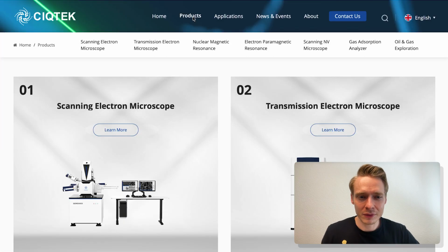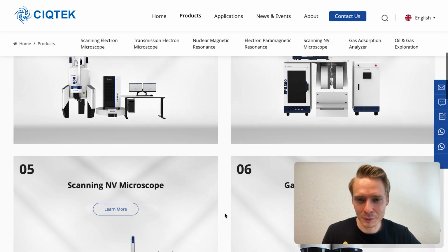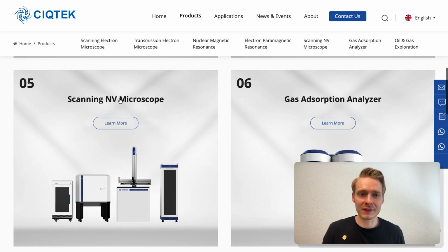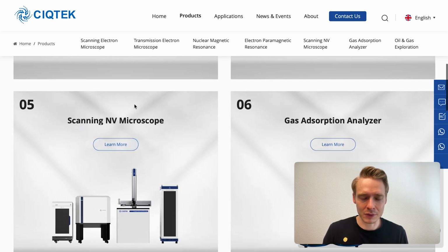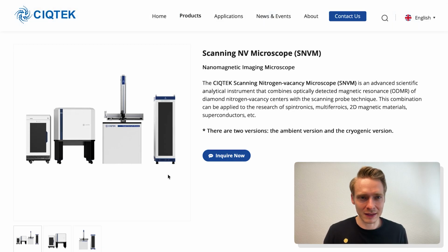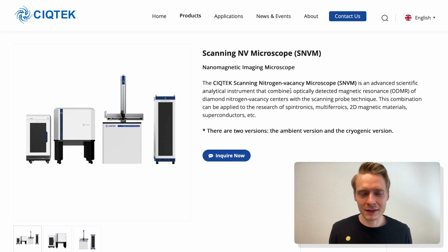Now, the other thing that I found interesting looking at the products, and let's see if we can see that in here as well, is these ones here. So the scanning NV microscopes, and that's what I wanted to quickly also talk with you about in today's video. So NV for nitrogen vacancy, and I think we've talked about that before, but I actually wanted to go into this again. So these are nitrogen vacancies that are usually introduced into a crystal, for example, a diamond, and the nitrogen vacancy behaves more or less like an artificial atom, which is sitting inside the crystal that can, for example, be optically measured. So you could use a laser to actually measure its properties, and it's also very sensitive to magnetic fields. So you can use it as a magnetic field sensor.